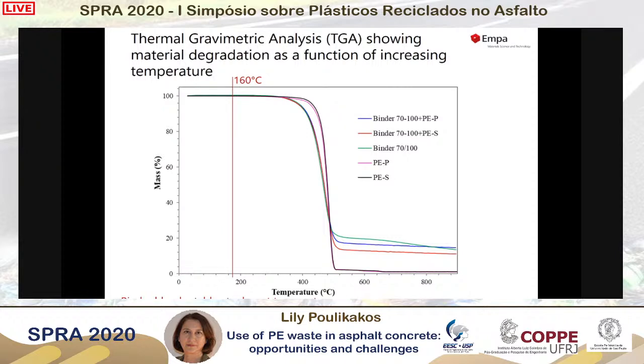However, as we increase the temperature, for example, as we start reaching 400 degrees, you see that the plastics by themselves, shown in pink and black, are a bit more stable. They are stable up to a higher temperature, and the blends, the base binder shown in green and the blends in red and blue, start to degrade sooner, at a lower temperature, until we reach about 500 degrees. There, the performance of the blends and the plastics by themselves diverge, and we see that the performance of the blends is affected by how much plastic is in there. The blue and the red show a different performance than the green. However, what is important for us to know is that at the relevant temperature, our material is stable.